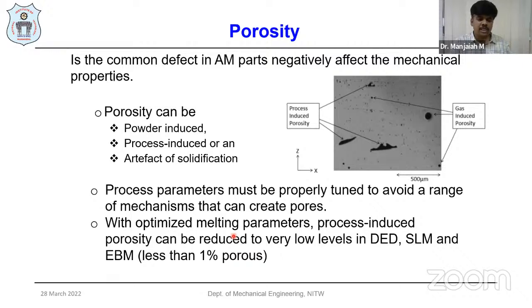In terms of other barriers or defects, you can see the porosity. Porosity is a very common tendency or common defect in AM parts, and it will negatively affect the mechanical properties of the components fabricated by AM. These kinds of porosities may be process induced, like lack of fusion and irregular porosities. And very spherical porosities are the gas porosities, the gas induced porosities. It may be inside the powder itself, or during the melting and solidification it may create these kinds of gas induced porosities.